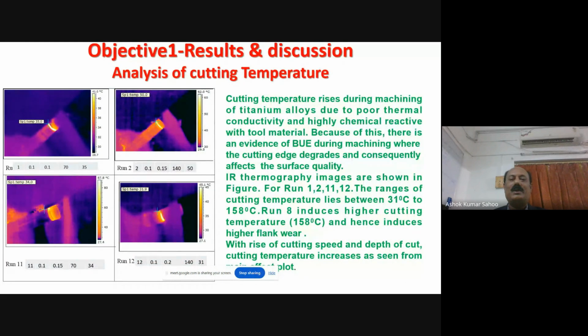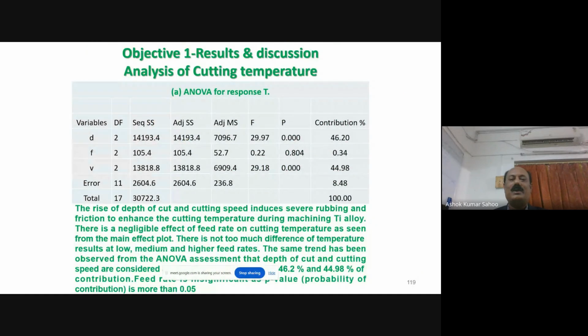For the cutting temperature generated during machining of titanium alloy, measured through an IR camera, it is within 31 degrees C to 158 degrees C. The maximum is 158 degrees C, where the flank wear is maximum. Depth of cut and cutting speed are found to be the most influencing parameters for the cutting temperature generation during machining of titanium alloy, as the p value is less than 0.05 and the contribution is maximum.